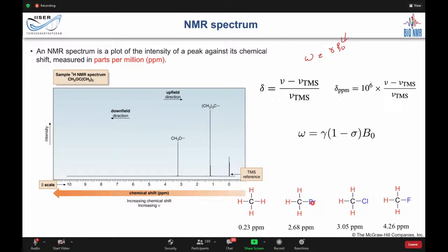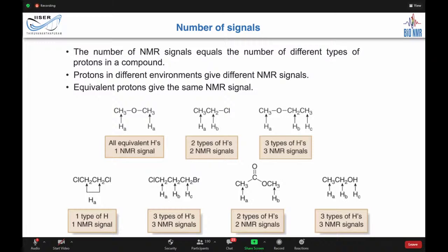If you replace this hydrogen with bromine, it comes at 2.68 ppm. You replace it with chlorine, more electronegative, 3.05 ppm. You replace it with fluorine, it becomes 4.26 ppm. So as you see, as electrons are withdrawn away from the hydrogen, the chemical shifts move to higher ppm values.